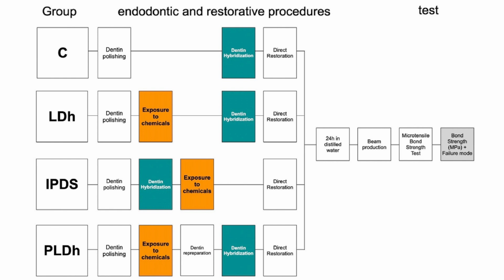The dentin hybridization was performed with a 2-step self-etch adhesive system, and a 0.5 mm thick flowable resin composite layer was applied for hybrid layer protection. Simulation of endodontic chemical exposure was by submerging in 5 ml of 2.5% sodium hypochlorite 5 times for 1 minute each, submerging in 2 ml of 17% EDTA for 3 minutes, and a final submersion in 2 ml of 2.5% sodium hypochlorite for 1 minute, and drying with absorbent paper, application of AH sealer, and waiting for setting for 10 minutes, and cleaning of excess with 95% alcohol for 5 seconds with a sterile coating swab. After that, direct composite restoration was done.